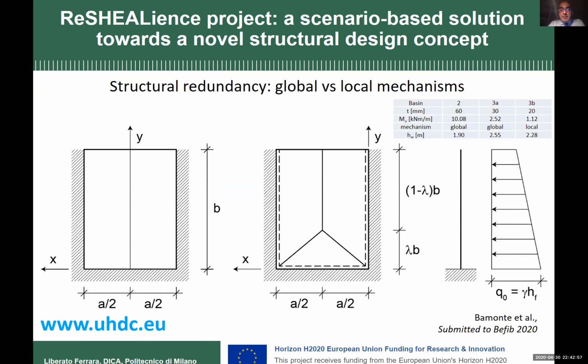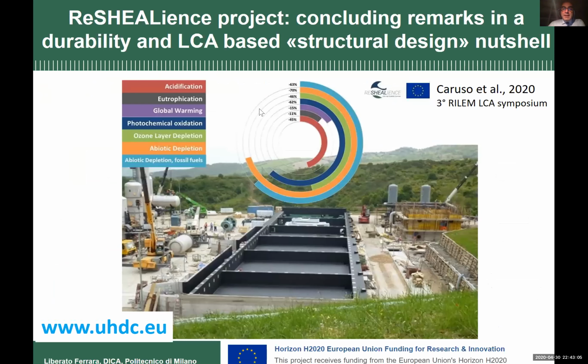This solution brings real advantages in terms of the 7 indicators of sustainability, because we use an extremely reduced quantity of material, and the material is self-healing, so has a longer service life. We have a reduction in acidification, eutrophication, global warming, and other indicators - 11% reduction in eutrophication, 45% in acidification, and 73% in the use of fossil fuels, because using less concrete means producing less cement, which is one of the most energy-consuming and CO2-emitting industrial operations.